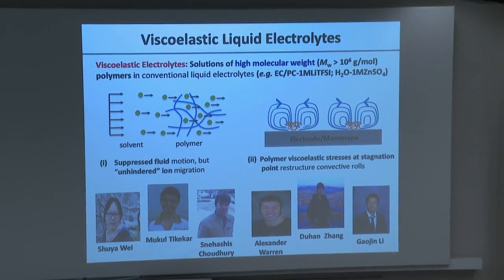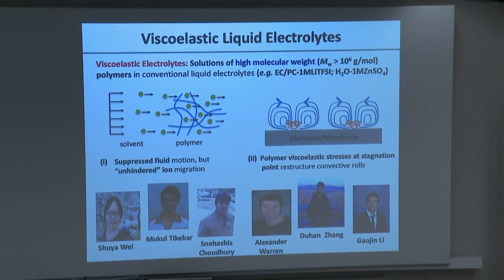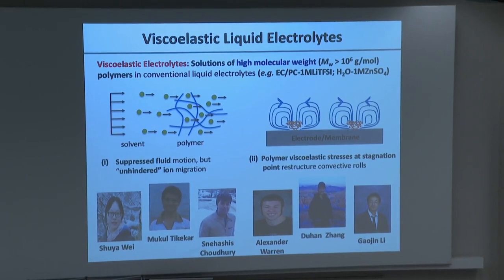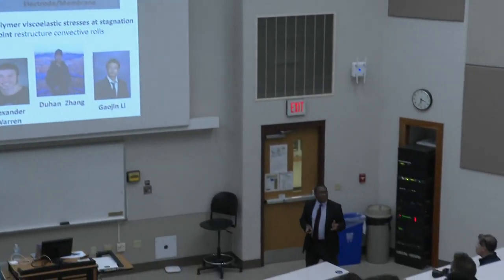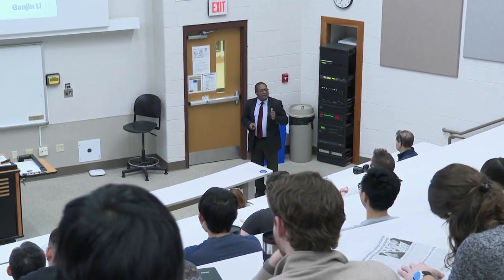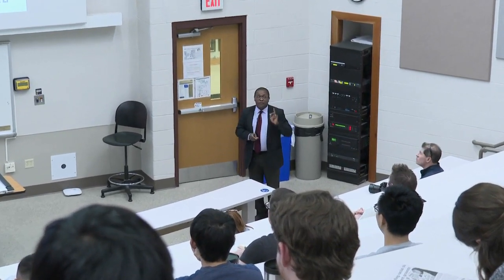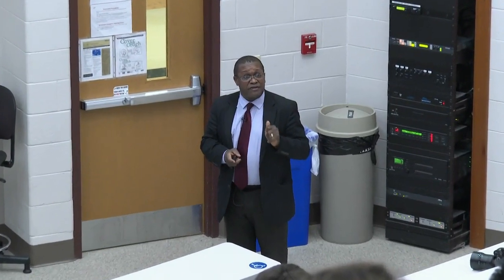So the reason I thought polymers were the answer is that polymers allow us to do two very interesting things, right? So the first is illustrated in this cartoon. We can create polymers in configurations that selectively stop the fluid from moving, meaning they provide a net, a high viscosity net, that stops the fluid from moving. But if the spacing between the net is large enough, the ions in the fluid can move as if the polymer is not there. Now, why is that important? We're trying to make a battery. And at the end of the day, if we stop the instability and also stop the ions, we've gotten nowhere, okay? So polymers that are entangled with big entanglement spacings, this is our kind of instinct, would be a good idea because it can stop the hydrodynamic flow that produces the eddies without compromising the ability of ions to get to the interface, which is what a battery needs to do.